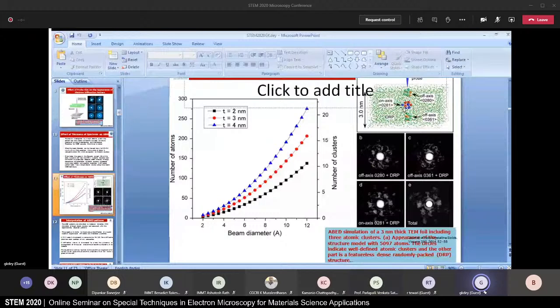Here is a plot which shows the number of atoms being examined as a function of the beam diameter. If you have a very small beam, and even if you have a slightly thicker sample, you are actually examining a very few number of atoms. That means fewer clusters. As you increase the thickness, the number of atoms being examined drastically increases, and that is not a good situation.